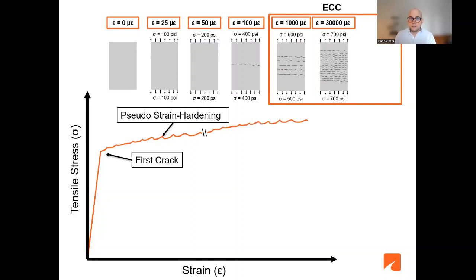Now, interestingly, you continue deforming this ECC, and it continues producing more tiny cracks, and the load capacity continues to increase. Eventually, you reach a point in which the material fails. One of these multiple cracks will grow, and the material will fail, similar to a conventional fiber reinforced concrete. But again, imagine the repair that we were talking about in the field for these culverts. If you have an ECC material, this is a very resilient repair, because even if you have some type of cracking, you know that these cracks are stronger than your original material prior to cracking, and it will be able to hold the load. So it's a very resilient system.